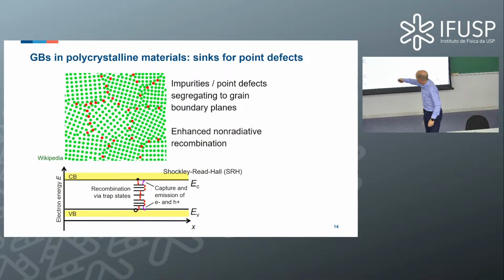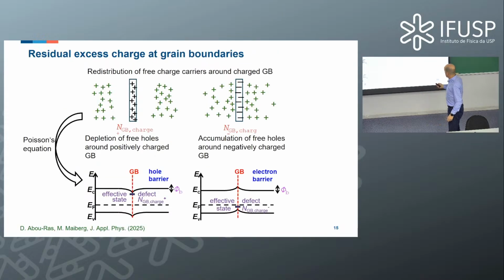So basically, if you have an excited electron and an excited hole in a semiconductor, they will at some point meet and then recombine, right? That's non-radiative because there's no emission of light. There's no luminescence emission. This is one important detail, and there's a second one. And this actually is linked to the fact that when we have defects at a grain boundary, they can exhibit a charge. It's not necessarily the case, but if you look at the ensemble of defects that are at grain boundaries, you have a certain excess charge, always. There's an excess charge density always present at each and every grain boundary, right?